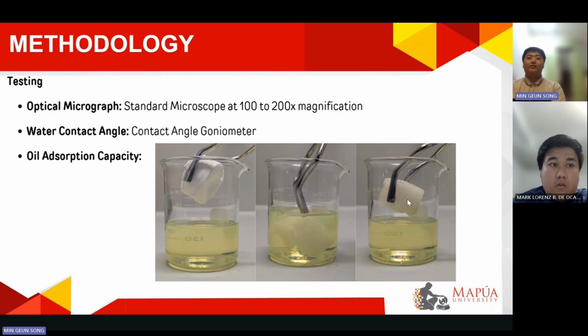The following tests were done to characterize the samples. First, we have the optical micrographs, which were done using a flat strip of the monolith and a standard microscope at 100 to 200 times magnification. The water contact angle was used to determine the wettability or hydrophobicity of our sample and involved using a similar strip of the sample and a contact angle goniometer, wherein a micropipette is used to place a small droplet of water for us to analyze the contact angle.